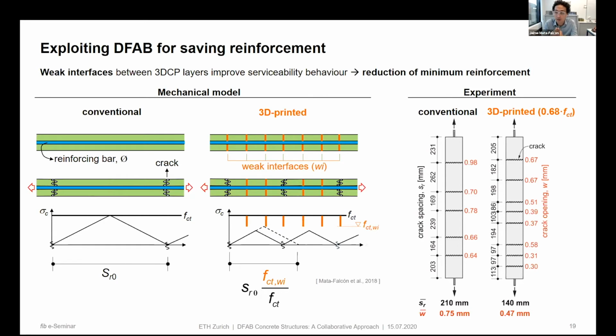There are certain things regarding the durability of reinforcement that are still not clear. But if we have a look just from the mechanical point of view, having these weak interfaces in our concrete plus continuous reinforcement, because we need this, otherwise we will not have a concrete structure, these weak interfaces are helping us because they can generate more cracks, a higher number of cracks. And you can see on the right, we have done some experiments that corroborate what we expect with simple mechanical models. When we have 3D printing with some reduced tensile strength in the interfaces, we have 30–40% smaller crack spacing and smaller crack width.